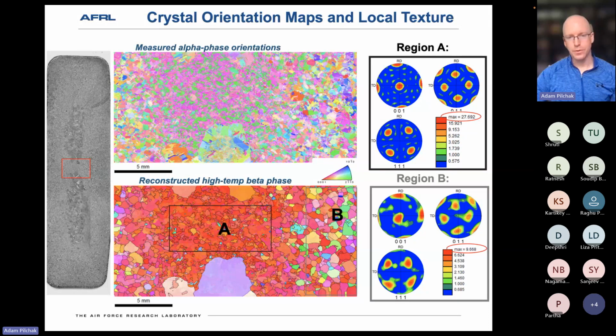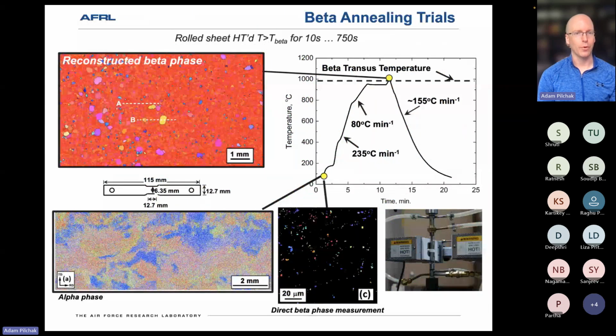So this was a really interesting data set to look at, because about 5 or 6, 7 years before that, working with my colleague Lee Semiatin, we were attempting to do really short duration beta annealing trials on rolled plate material to produce a fine recrystallized beta grain size to study the effect of grain size on development of transformation textures. And when we did that, we were beta annealing for 5 seconds, 10 seconds, 30 seconds, a minute, 2 minutes, very short durations. And so we had this series of snapshots of what was happening at the earliest stages of recrystallization, and this single crystal-like texture in region A really struck me as something that I'd seen before.